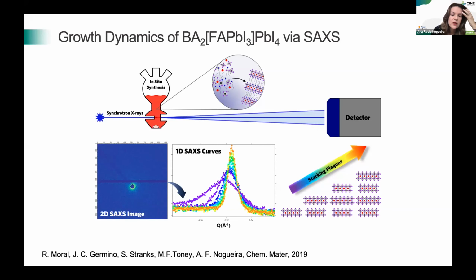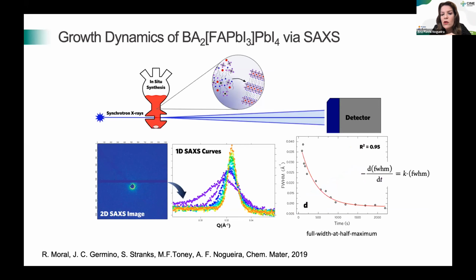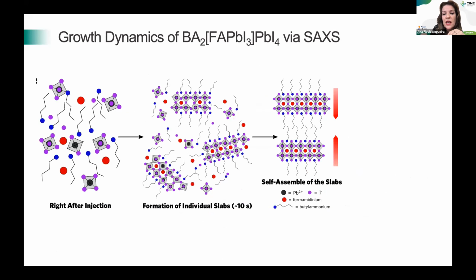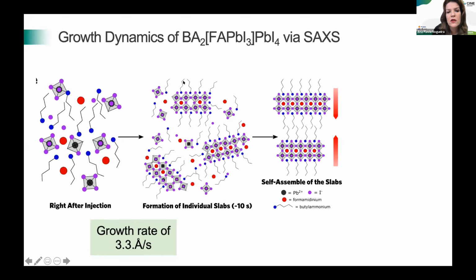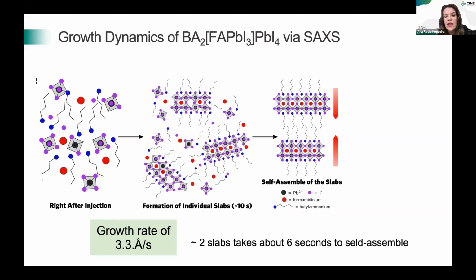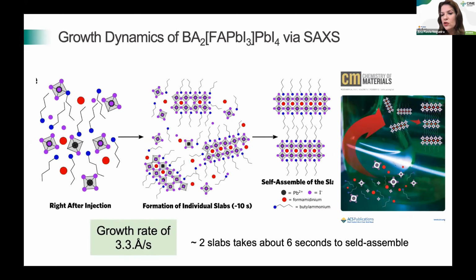But also, as I mentioned, because we're doing this with time, we can do some kinetics with our data. For instance, you can look at how the full width at half maximum varies with time. We can do some calculations here, and you can even calculate the growth rate of these materials. For instance, we know that right after injection, we have the solution of the precursors. Within 10 seconds, we have the formation of individual slabs. In this case, for these perovskites, the slabs are formed by 2 layers of octahedra. So n is equal to 2 here. And after that, you have the self-assembly of these slabs into very nice 2D structures. We can even calculate that 2 slabs take about 6 seconds to self-assemble here. This work was the front cover of Chemistry of Materials in 2019.